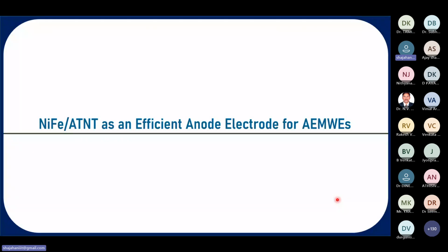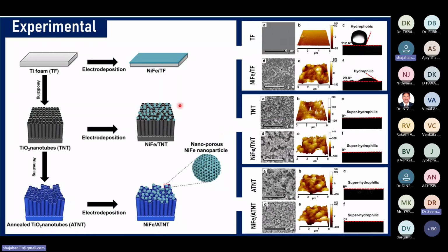Initially for the anode electrode, we prepared an ATNT substrate, annealed titanium oxide nanotube substrate, as a superhydrophilic electrode substrate. Then we deposited nickel iron catalyst on ATNT and used it as the anode electrode for AEMWE systems. So how did we prepare that nickel iron ATNT? We took titanium felt from a company, and we did anodizing to make superhydrophilic electrodes. After the anodizing process, we got titanium oxide nanotubes. We gave the name TNT.